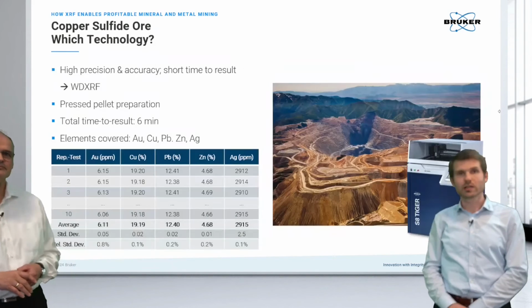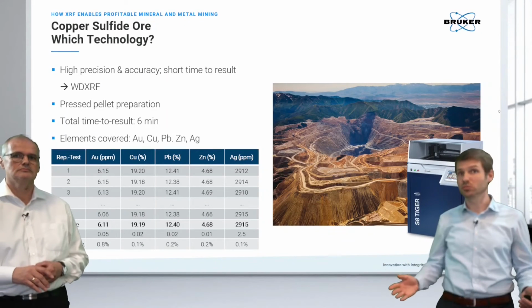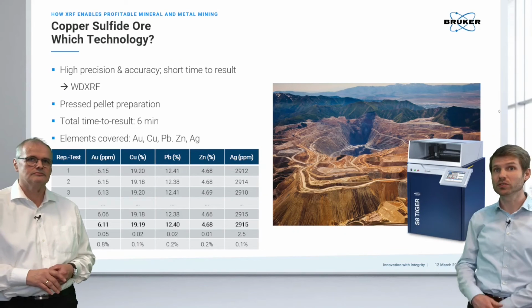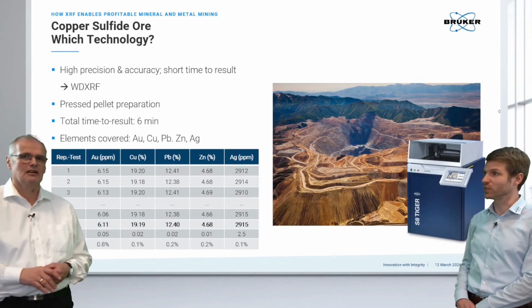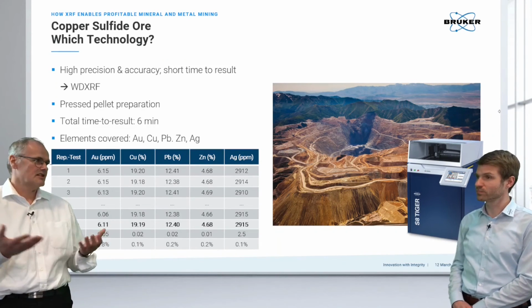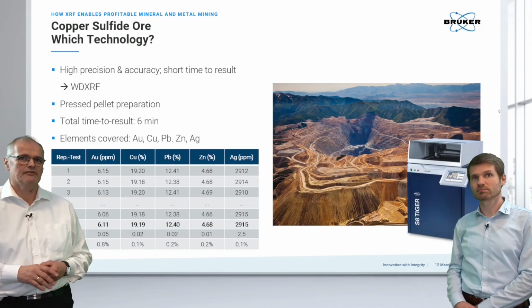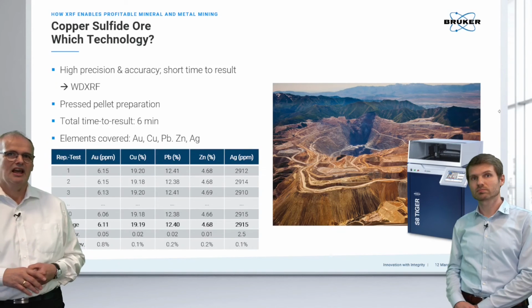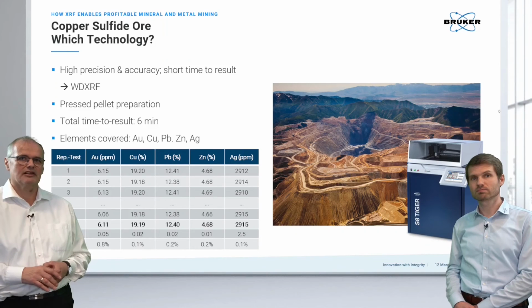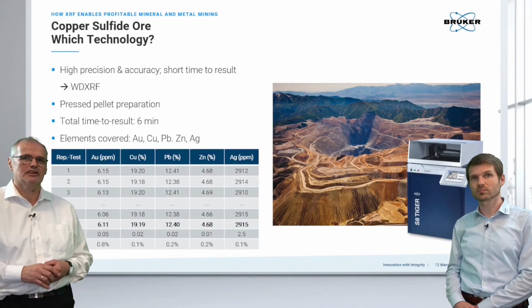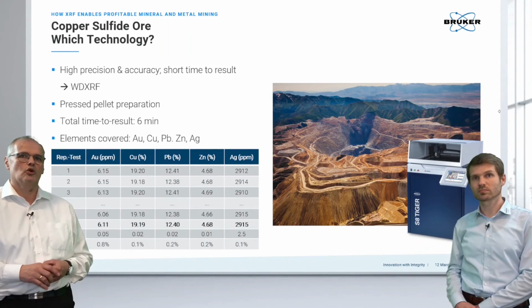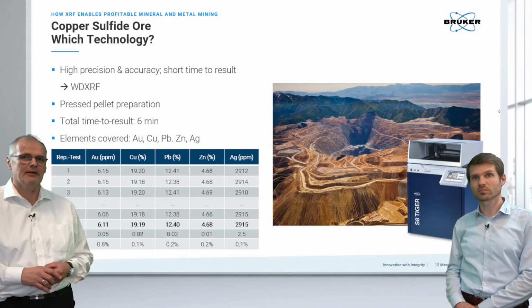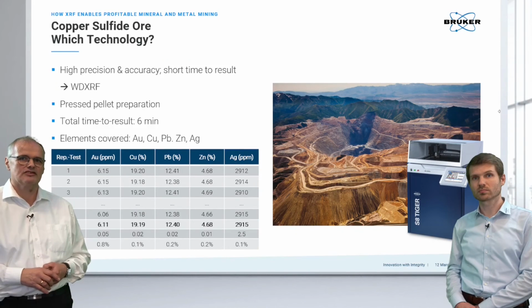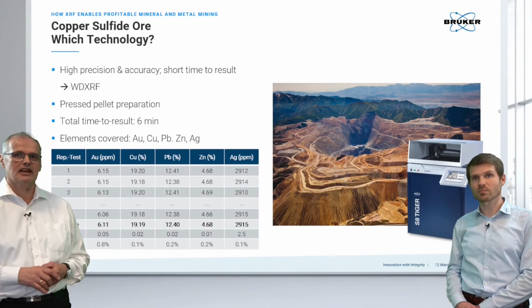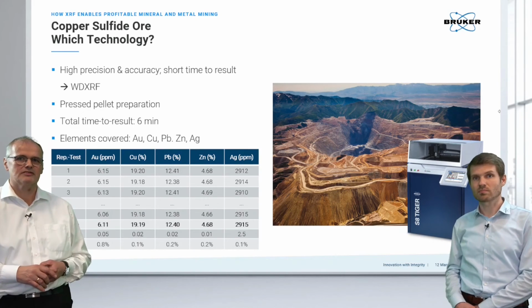Yeah. Switching back to concentrates, if we do this with a pressed pellet, what type of device do we use there? Yeah, it's basically milling. We have a powder, and then we use a press. We look here into a method from the Latin Americans, looking into gold in the range of a few ppm. Copper, of course, it's a concentrate of about 20%. Then we have a little bit of lead, zinc, and also silver in the range of 3000 ppm.